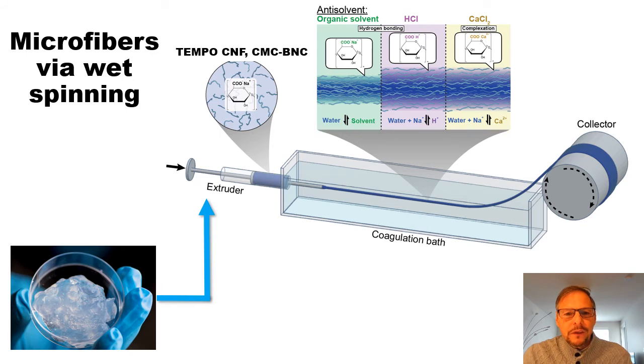Here we can use different types of cellulose materials, but of particular interest is BNC that is extruded in a coagulation bath. In that case, imagine that in the syringe we have bacterial nanocellulose dispersed in water and it's injected as a dispersion in a coagulation bath that contains water either with HCl, calcium chloride, or maybe you can imagine that the coagulation bath is simply an organic solvent like maybe acetone or ethanol. So what is going to happen is that the bacterial nanocellulose, or in general the cellulose ribbons, will coagulate and will form a thread or a filament that you can collect.